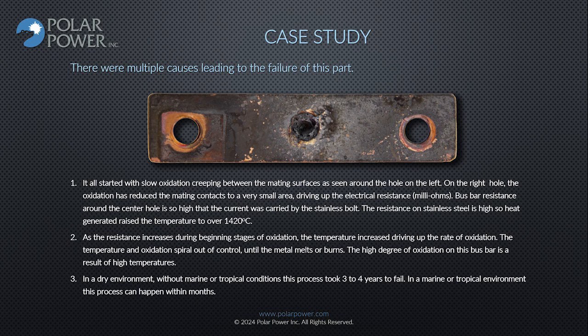As the resistance increases during beginning stages of oxidation, the temperature increased, driving up the rate of oxidation. The temperature and oxidation spiral out of control until the metal melts or burns. The high degree of oxidation on this bus bar is a result of high temperatures. In a dry environment, without marine or tropical conditions, this process took 3 to 4 years to fail. In a marine or tropical environment, this process can happen within months.